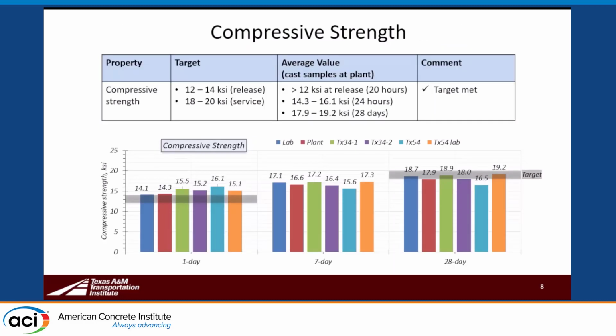So this is a look at compressive strengths. We did have a requirement at 1 day as well as 28 days. By and large, if we look at the various bars that we're showing here, lab mixes are shown in blue, and the plant trial batch is shown in red. Texas 34s and 54 are the girders that we cast individually on different dates. And then we did a lab mix with a new cement that was being used at the plant after we cast the 54 to make sure that in the lab we were getting similar results.